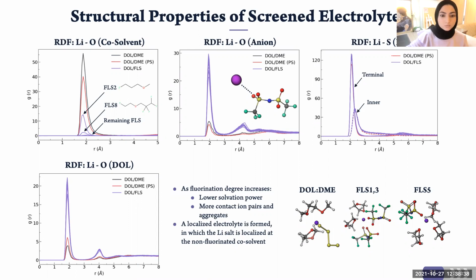So some of the top solvation structures are also shown here, where in the conventional electrolyte, we see mainly solvents in the cation solvation shell. In the fluorinated solvents, we can see that anions are introduced. So in the fluorinated solvents, we conclude that there is a localized electrolyte that is being formed, where the lithium salt is localized in regions that do not have fluorinated solvents.